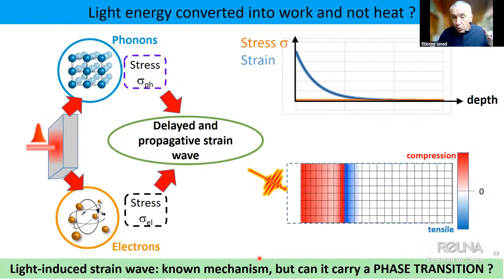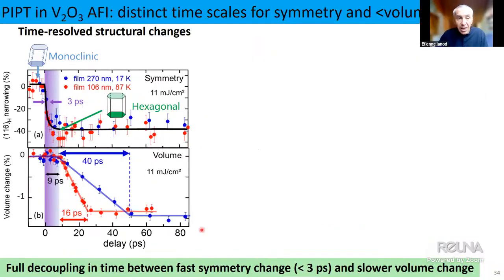This strain wave mechanism is quite well known, but what is not known at all is: can this phenomenon carry with it a phase transition? To answer this question, we need to look at a time trace of the evolution. Here, what I show is the evolution of the width of the 116 Bragg peak, which narrows due to the insulator to metal transition, and also the unit cell volume of the material. Let's concentrate first on the narrowing of the 116 Bragg peak. What you see here is that after roughly 3 picoseconds, we have a full inverse ferroelastic transition, and we restore the symmetric hexagonal phase expected in the metallic phase.